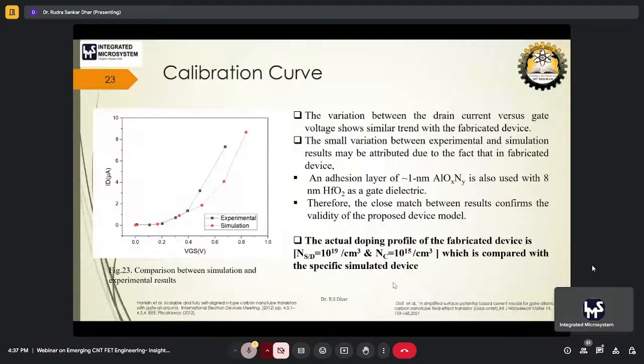The small variations between experimental and simulation results are due to the fabricated device, due to the addition of 1 nanometer aluminum oxide, and the hafnium oxide used as the gate dielectric. Therefore, the close match between the results also confirms the validity of the device that we are using here. The actual doping profile of the fabricated device is also mentioned. Source drain, we are using 10 to the power 19, and 10 to the power 15 for this particular calibration. That is what we did.